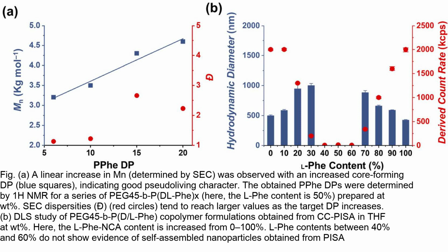The nanoparticles obtained from homochiral formulations had a DH of approximately 500 nanometers, indicating the formation of well-defined vesicles. These results indicate that the chirality of the core-forming monomers affects the reaction kinetics and the size distribution of the self-assembled nanoparticles.